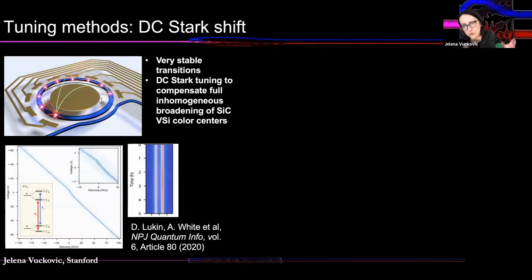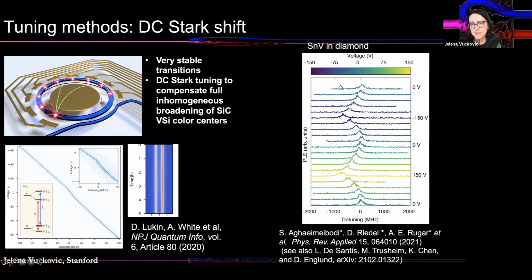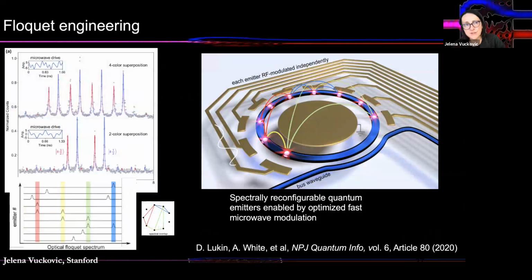And then for spectral tuning, we developed a tool set of different techniques, and there are even others beyond the ones that our group has developed, but we recently primarily focused on electrical shifting, Stark shifting of these color centers, and we can do that for silicon carbide color centers. Here you see how we can tune Stark shift by putting an electrode and applying voltage. The color center transition shifts by a few hundred gigahertz, which can compensate for all of the inhomogeneous broadening. And color center transitions are still stable over hours time scale. So that's really good. It's not degraded in the process. And the same type of Stark shifting also works for color centers in diamond, as we recently showed for tin vacancies in diamond.